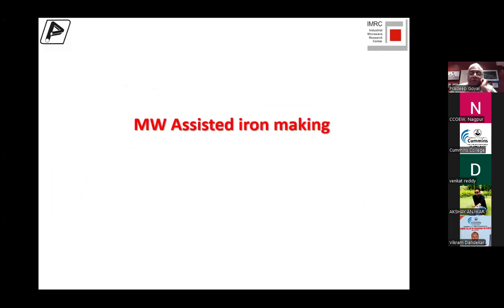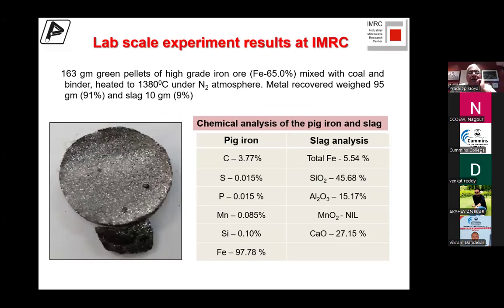Now, let me come to the main portion that I was asked to speak on, which was microwave assisted iron making. Right? So we started with very small green pellets to melt in the microwave oven. We took these green pellets of high-grade iron ore mixed with coal. Now, mind you, all steel mills use coke for reducing the iron ore. But we never used coke. We always used coal, because coke is very difficult and very expensive. And we used some binder, and we were able to melt the pellet very comfortably to get iron and slag.